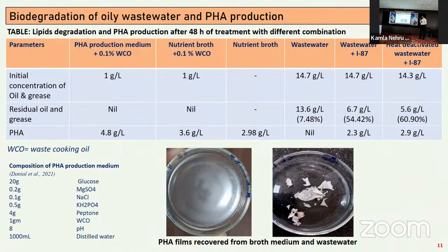So after treatment the results were as follows. If you see, the initial concentration of the wastewater in terms of oil and grease was around 14.7 grams per liter. This is after dissolved air flotation. So a lot of oil is really going into the drain and causing secondary problems. So we saw that in the PHA production medium, that is the synthetic medium, containing 1 gram per liter of oil.